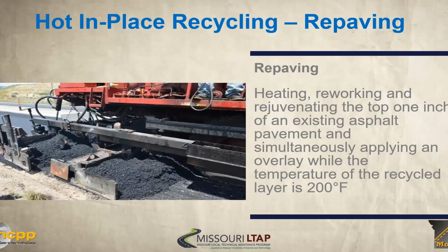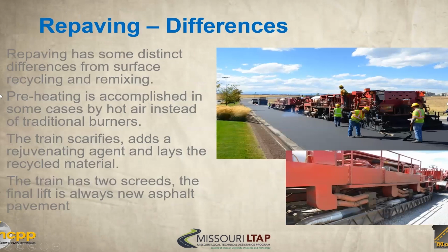So this final strategy is called repaving, and repaving is different from remixing in that we're heating, reworking, and rejuvenating the top 1 inch of an existing pavement, and simultaneously, as you can see from this, we have 2 screeds placing the virgin mix over the recycled mix. So here is the recycled material, here is the virgin material. That's the distinction, and it has some distinct differences as well. In this instance, this preheater is using hot air instead of traditional burners. The train is scarifying, adding a recycling agent, and then laying the recycled material. And like you saw, the train actually has 2 screeds, so the final lift is always new. In this repaving process, it's always new asphalt.